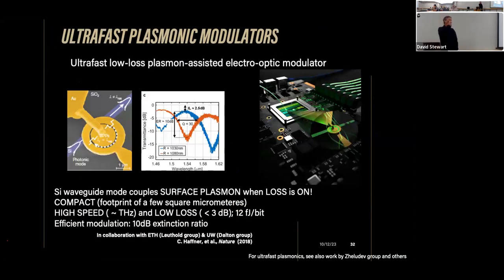But the point I'd like to make is that plasmonics makes processes much faster. And let me first mention this work we did with Juerg Leuthold at ETH, who actually pushes for using plasmonics or nanophotonics quite strongly, and he's, I would say, a leading person in this effort. So here we use this gold ring resonator, where in the ring we place an electro-optic organic material, which changes its refractive index when you apply voltage.